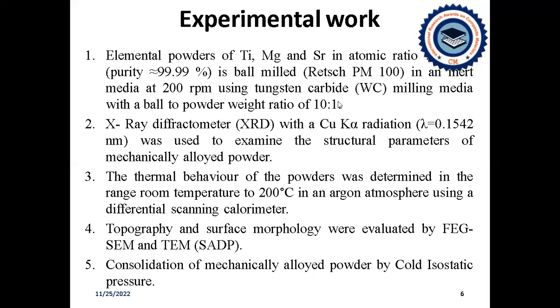It is mechanically alloyed using the high energy ball milling process, and later the alloyed powder sample was subjected to the structural investigation using the X-ray diffractometer.